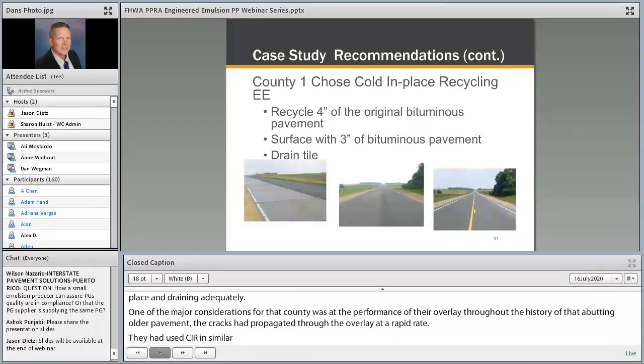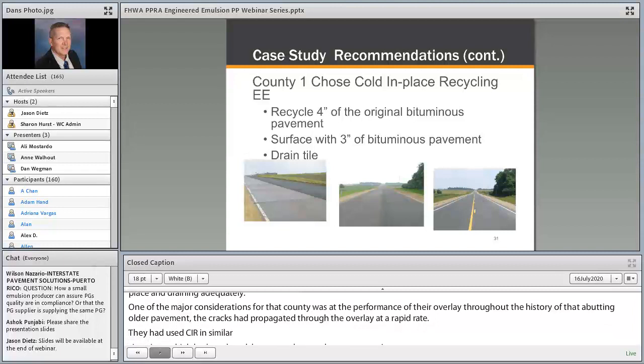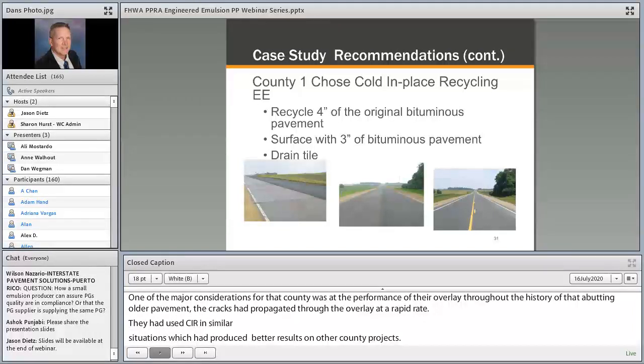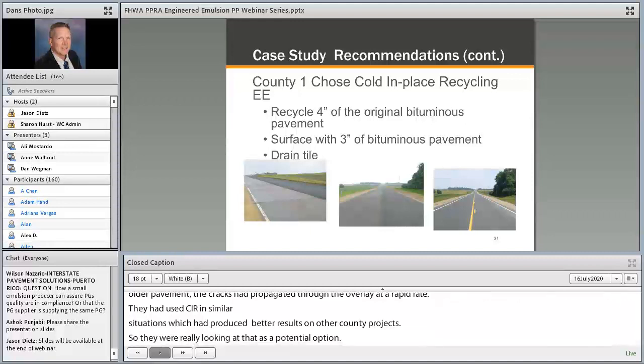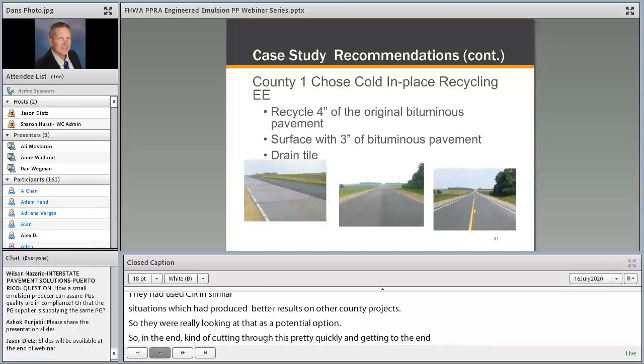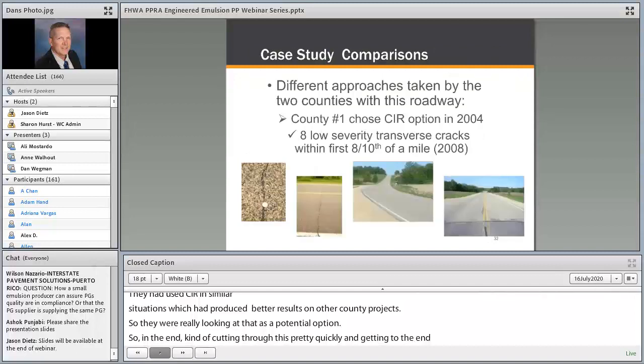So in the end, kind of cutting through this pretty quickly and getting to the end result, County 1 chose cold-in-place recycling utilizing an engineered emulsion and recycled 4 inches of that original bituminous pavement and surfaced it with 3 inches of new hot mix on top. They did install drain tile to further aid that drainage on the roadway.